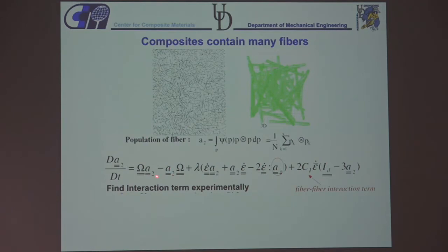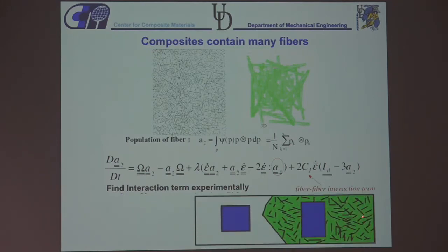So you see there are very similar things that were in Jeffery's equation, but it is now extended to an orientation state, and we introduce what we call a fiber-fiber interaction parameter because the fibers are close to each other and they're going to interact. So this interaction coefficient is going to depend on fiber volume fraction, it's going to depend on the concentration, and so forth. But it's a phenomenological parameter. We don't know how to find this from first principles. But we could come up with experiments to characterize it and so forth. And then we can predict the orientation of fibers in a flowing suspension for short fiber composites.